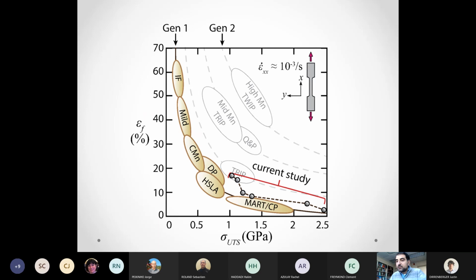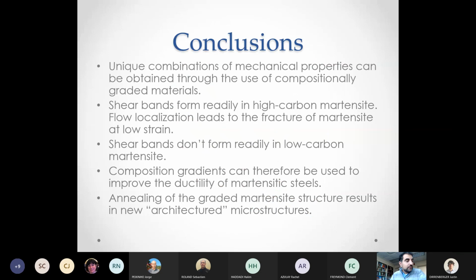If we look at a traditional diagram showing the strength and ductility combinations we can achieve, you can see how we can expand a little bit those bubbles that are possible now by using the graded materials. I think I should save some time for the discussion, but I just want to highlight how we can use non-uniform materials, materials with differences in microstructure, and achieve mechanical properties, corrosion properties, electrical properties that are superior to the ones we can have using homogeneous or uniform materials.